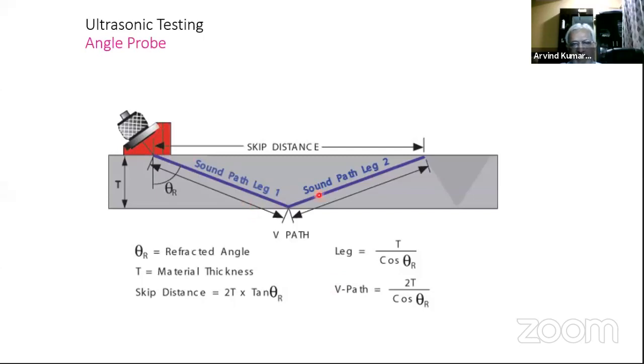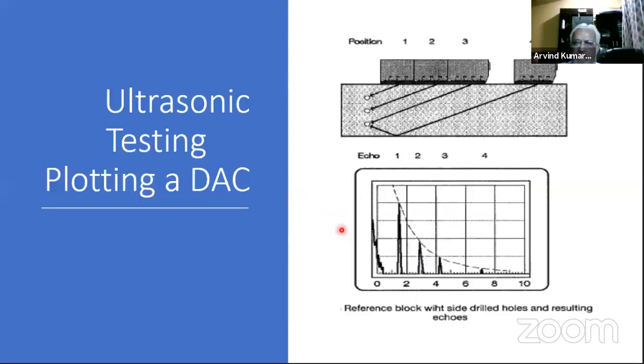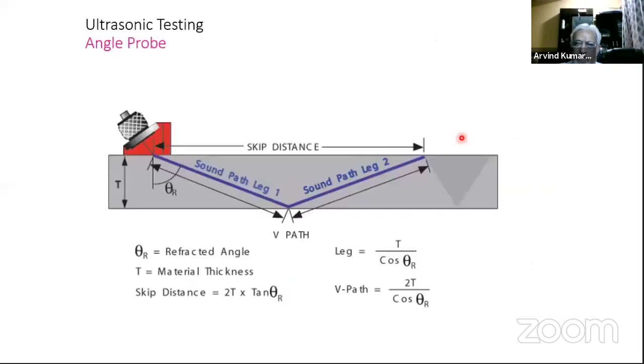These are some of the simple trigonometric formulas that we use for calculating the distances. You have surface skip distance. Skip distance is what we call it when the beam from my probe hits the root, meaning the back surface of the material. When it hits and bounces back to the surface, it forms a full V, so I call it a full V path. The full V path where I get the indication on the top surface, I call the skip distance. So this is my total skip distance.